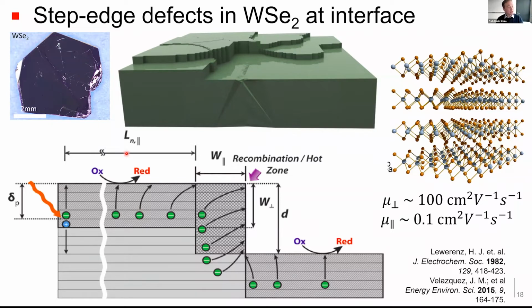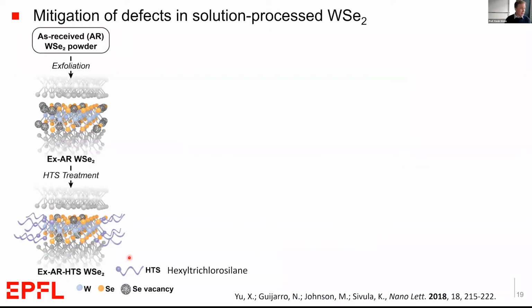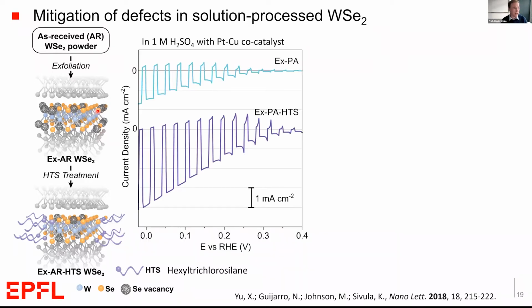So one way to overcome that is to chemically passivate these edge sites, and we did that using this hexyl trichlorosilane chemical, which we can functionalize the selenium vacancies on the edges of this flake. And this has a positive effect on the photocurrent, as shown here.